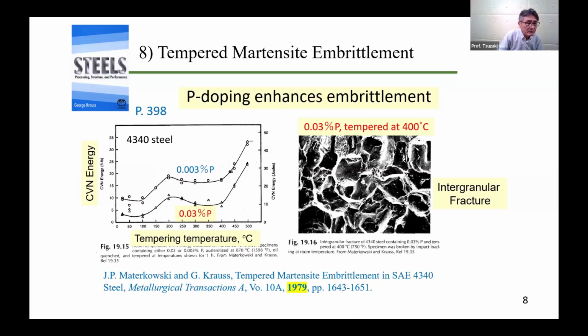The embrittlement is enhanced by P doping like this. And as shown in the right figure, the fracture structure is characterized by intergranular fracture along prior austenitic grain boundaries. This has been attributed to segregation of phosphorus to grain boundaries during heat treatment and the resulting reduction in cohesion.